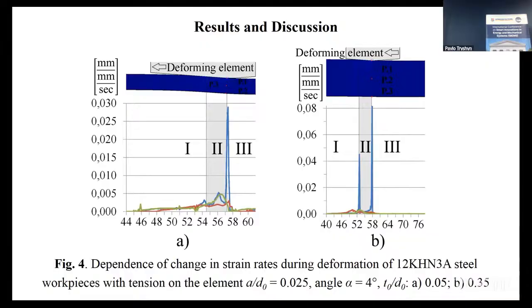Figure 4. Dependence of the change in strain rate during deformation of 12KHN3A steel workpiece with tension on the element A over D0 equals 0.025, angle alpha equals 4 degrees. T0 over D0: A, 0.05; B, 0.35. Figure 4 shows that intense deformation is observed when the contact area translates to the non-contact zone behind it. Obviously, there is a zone of local plastic deformation here. The strain rate increases to a value of Xi equals 0.03.